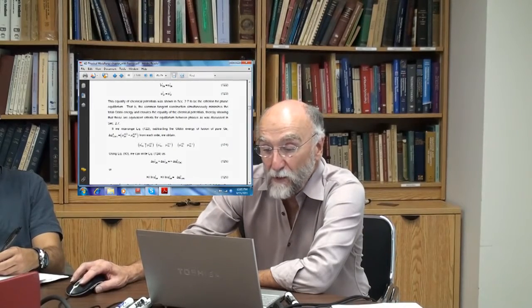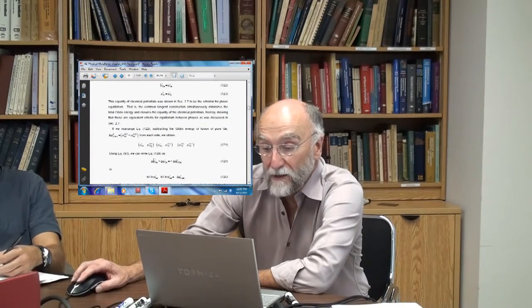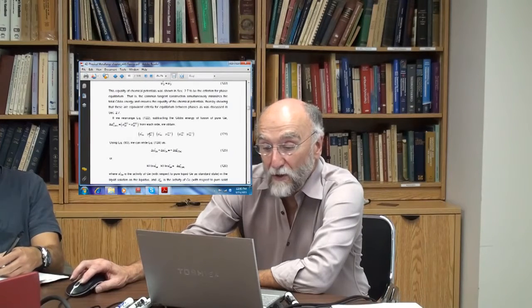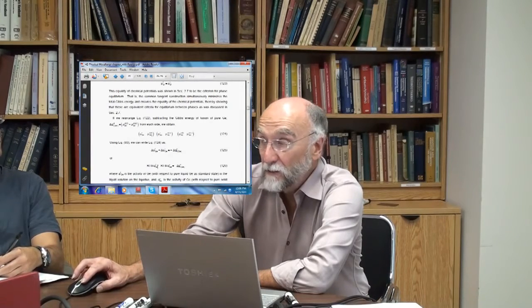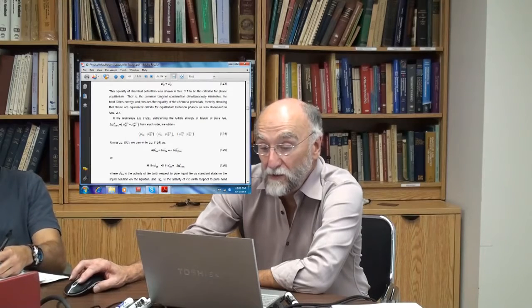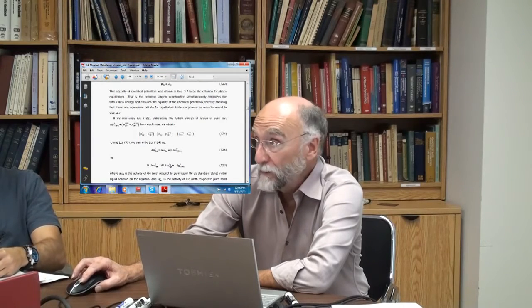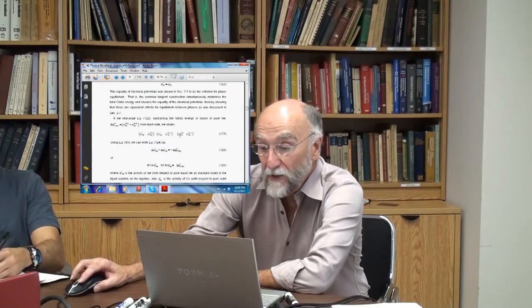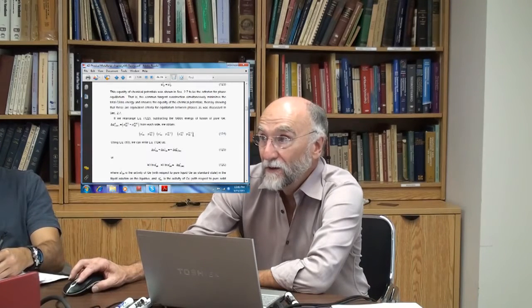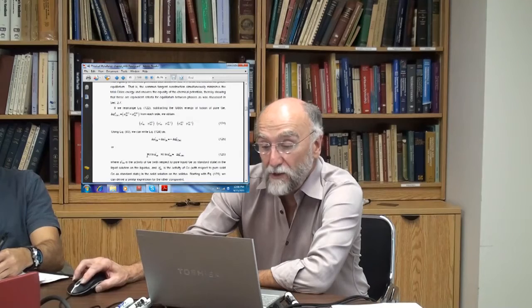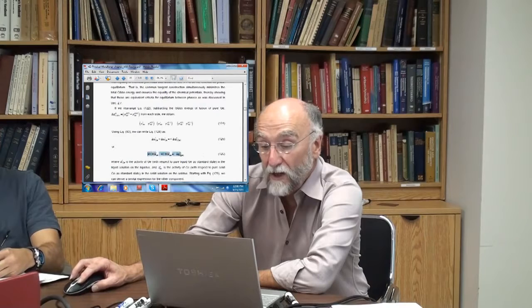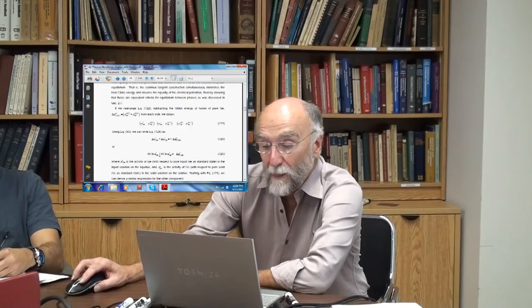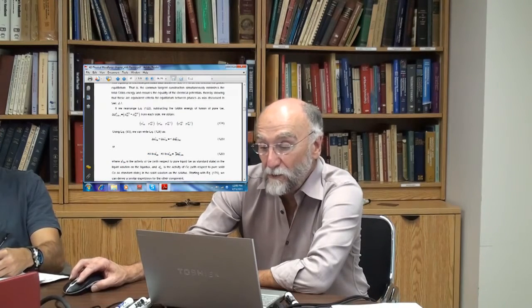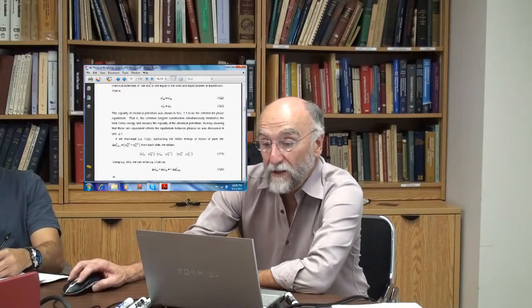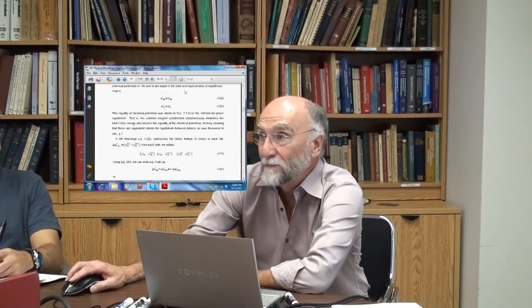Okay, so mu minus mu naught is delta mu, or RT log activity. So this is delta mu of the liquid, or RT log activity of germanium in the liquid. This is delta mu of the solid, which is RT log activity of germanium in the solid. And mu minus mu naught here is the Gibbs energy of fusion of the pure material. So you have this equation here, which is simply another way of expressing this equation: RT log activity of germanium on the liquidus, minus RT log activity of germanium on the solidus, equals minus the Gibbs energy of fusion. It basically just comes from this equation. Nothing new has been added.